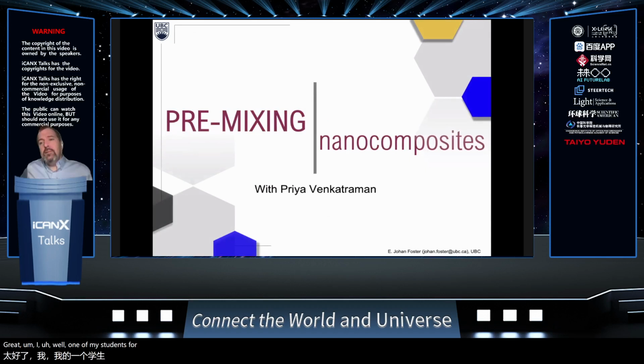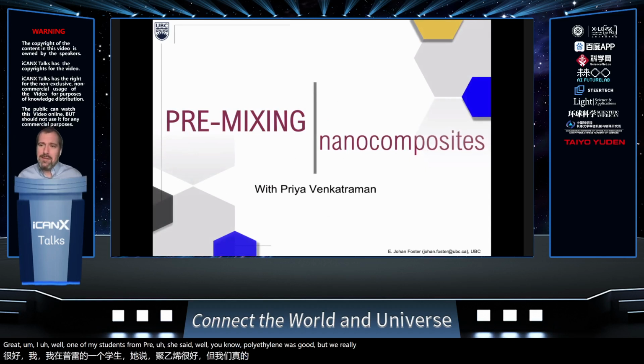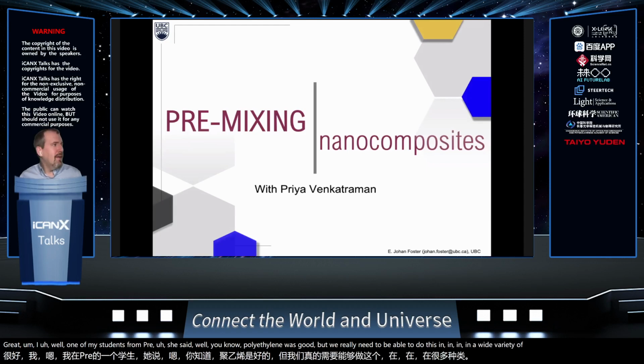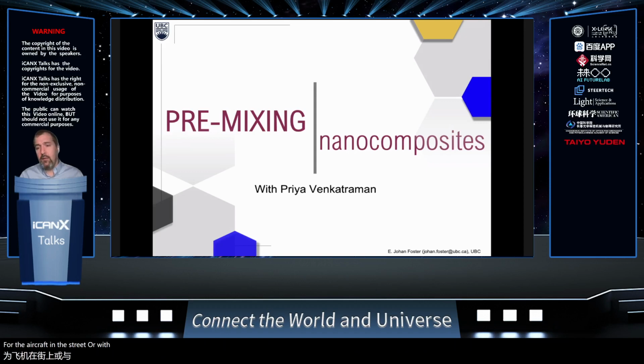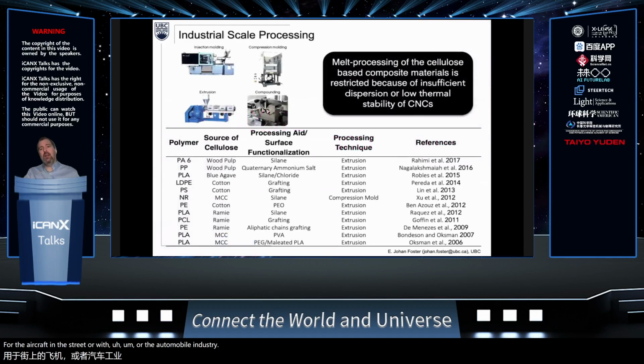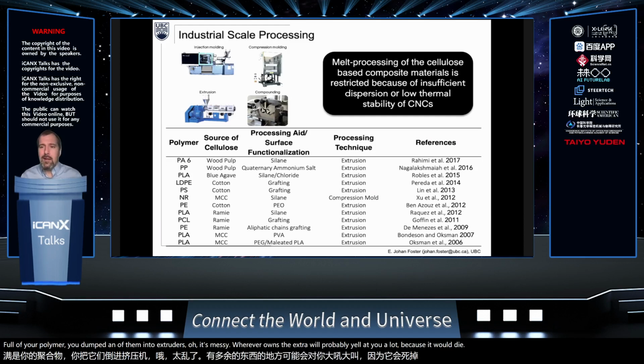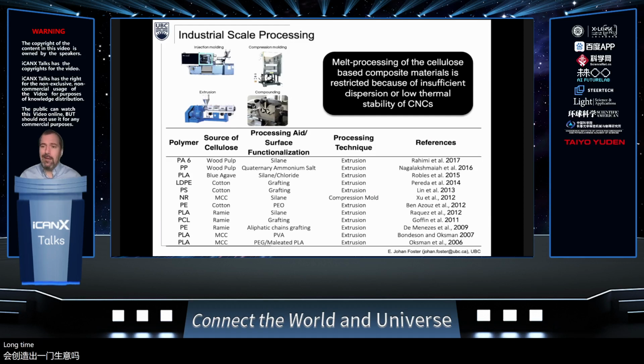One of my students, Priya, she said, well, polyethylene was good, but we really need to be able to do this in a wide variety of manners. She wanted to reinforce plastics for the aircraft industry or for the automobile industry. Okay. She said, well, okay, we can put catalysts on there, but can we put them through an extruder? And this is problematic. Okay, so if you just take a container full of cellulose nanocrystals and a container full of your polymer, you dump them into an extruder. Oh, it's messy. Whoever owns the extruder would probably yell at you a lot because it would create a big mess. Okay, long time cleaning the extruder. We tried it a couple times. Showed that it really didn't work.